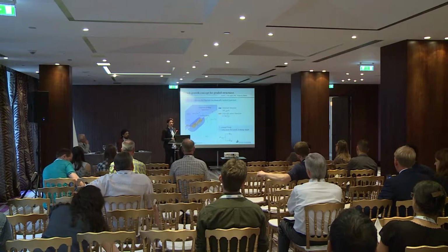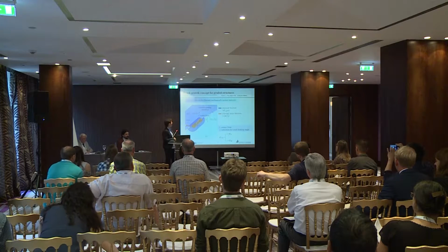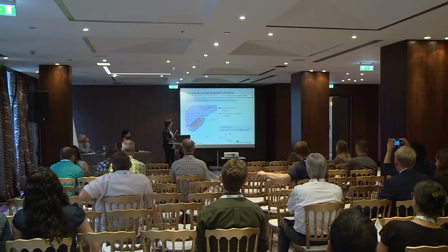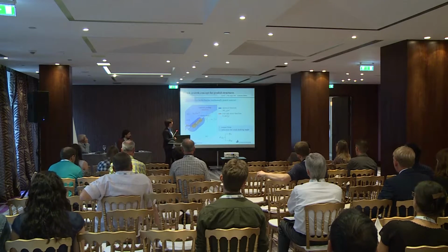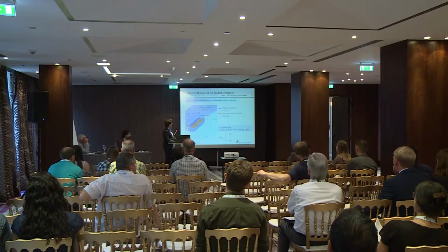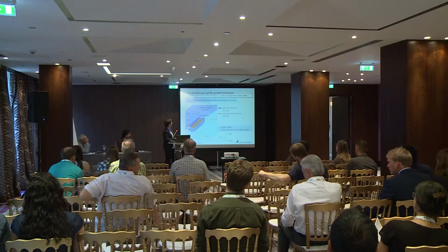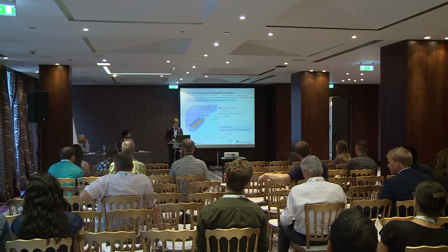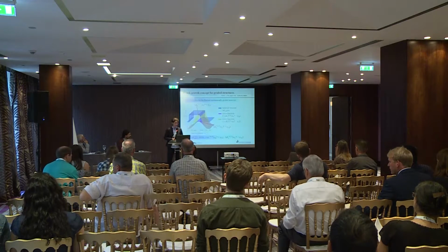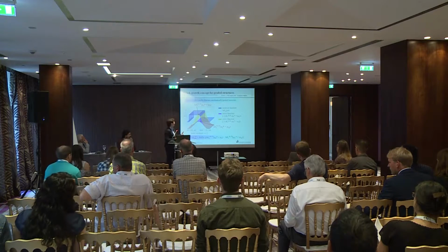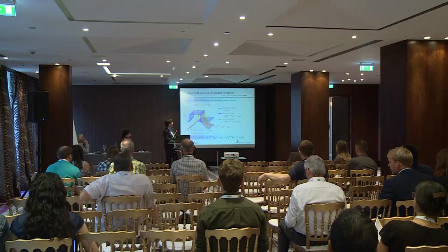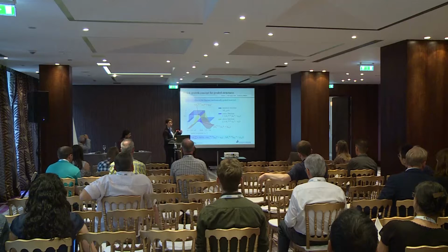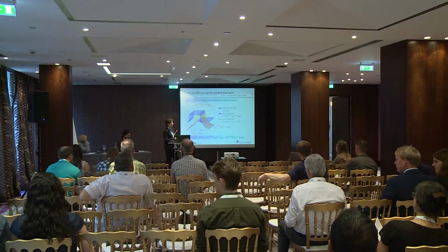So now what I need is a relevant stress function. It gives me a hint at what time this crack will grow at all and in what kind of direction. This hint is given at the first contact with the material function. It's easily said, but how do I get this function? Therefore I plotted three functions. First of all, here again, the material function I've shown you earlier. You can see there's this jump at 30 degrees, which means I've got a transition grading at an angle of phi 30 degrees.